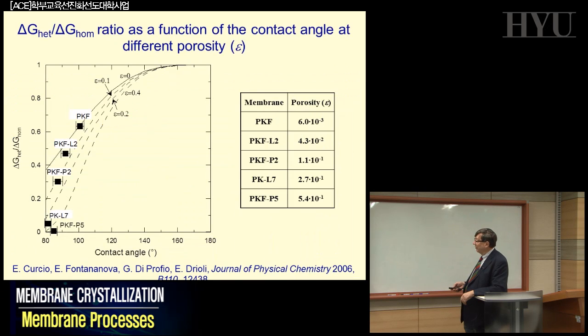And that is this kind of curve, the level of this curve, which is also a function of the hydrophobicity or hydrophilicity and of the size, can have an effect in some deviation of this kind of equation, which is the modified Young equation. But now we understand that this equation is related to the delta G of our system, and is related to the kinetic of the crystal growth, which normally people were not considering in traditional studies on this kind of effect.